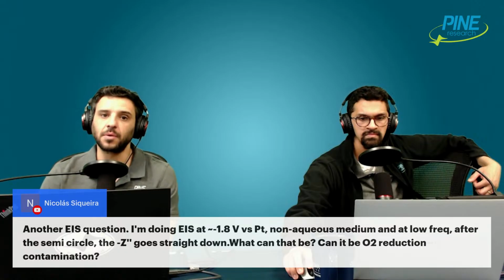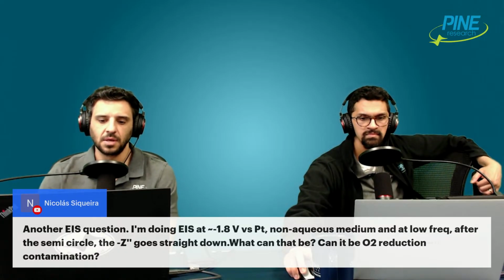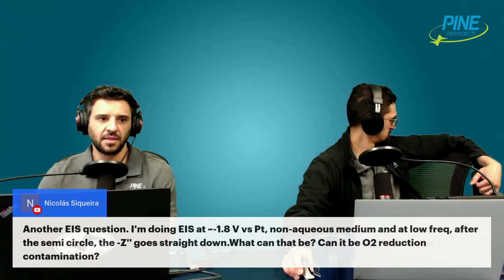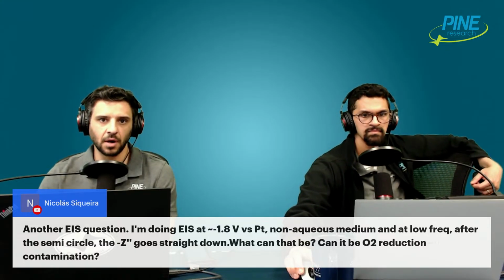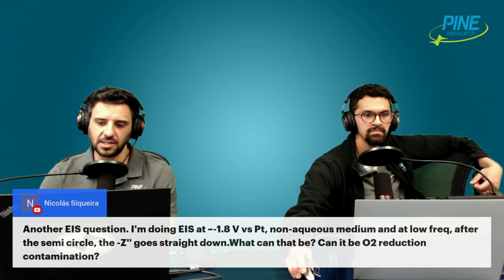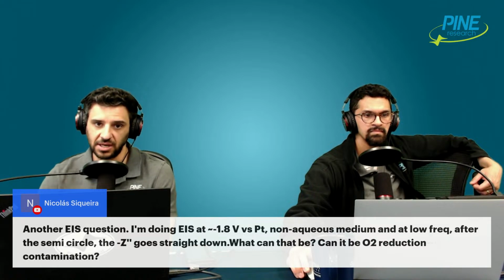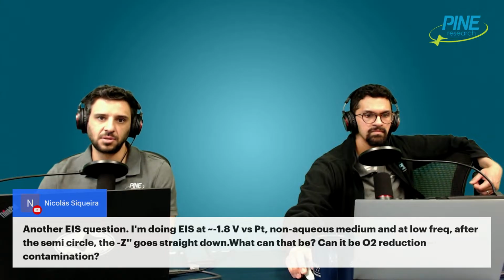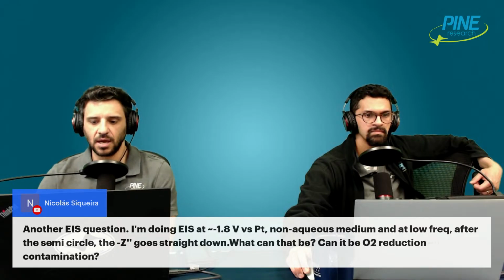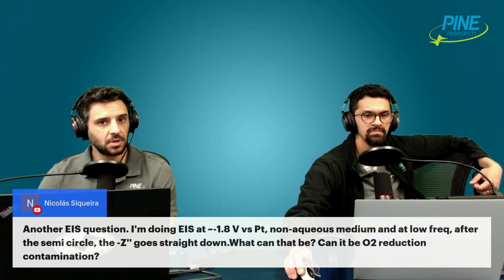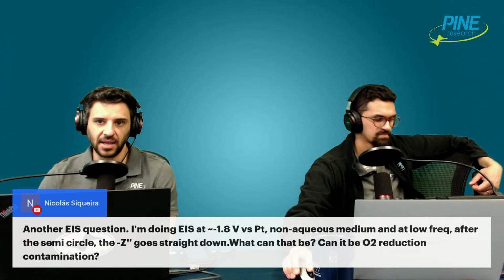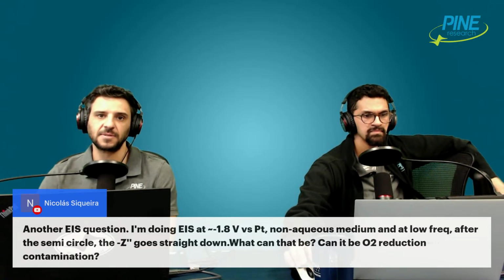Do Kramers-Kronig and see if the results are matching at those frequencies with your Kramers-Kronig results. Because I would have heavy doubts that, especially as the frequency drops farther and farther, you have valid impedance any longer. There's probably a lot of drift happening, and it's probably getting away from validity. However, if it is valid, that tends to indicate some kind of inductive process. As the imaginary impedance axis goes down, becomes more negative, that indicates some sort of inductive process. Now, why?